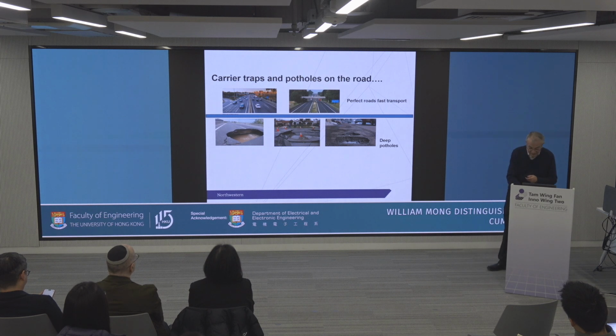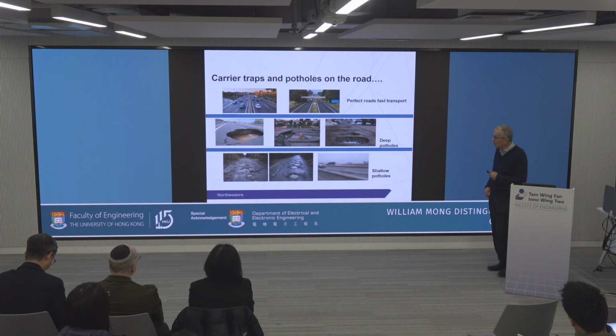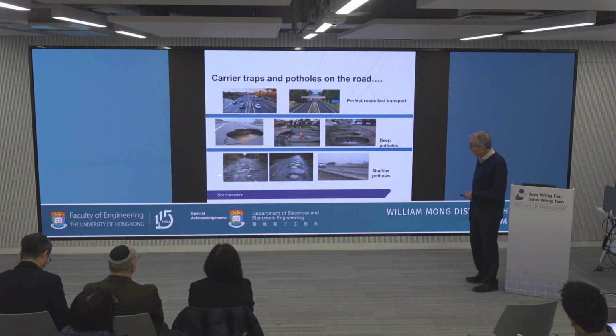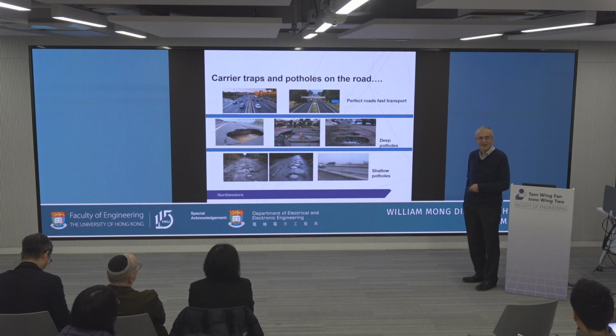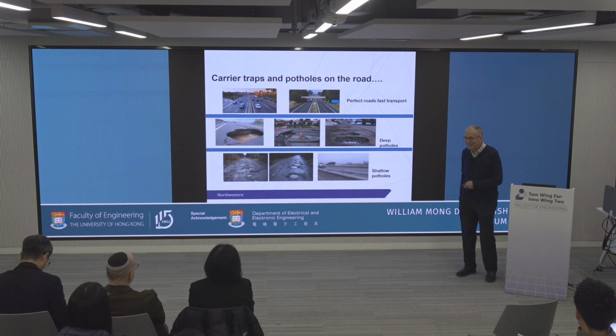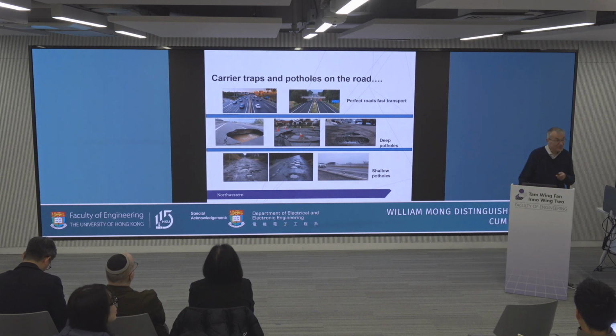The perovskites have shallow traps, or almost no traps. So this is the perovskite. The highway looks lousy. So mobility actually is not very high. Mobility of perovskite is 20 times, maybe even 50 times lower than silicon. So you're not going very fast. But the traps, these are not traps. They're very shallow. You have to drive carefully, but you're going to get there. Okay? So that's the difference between the two.